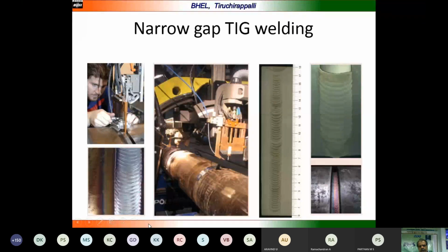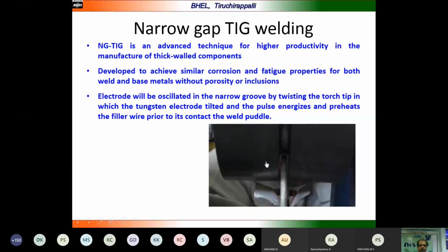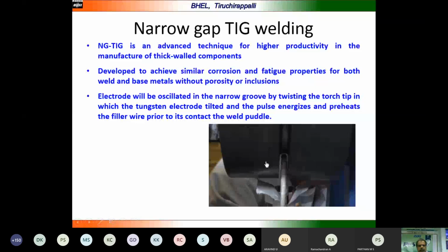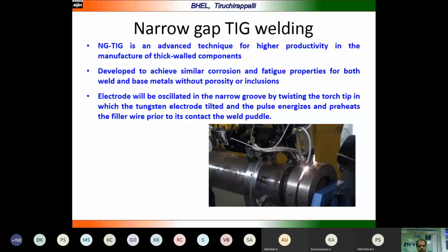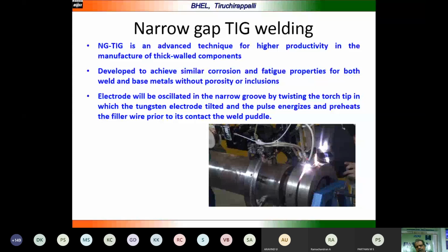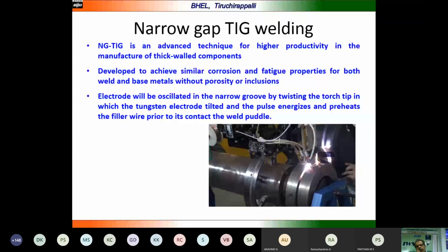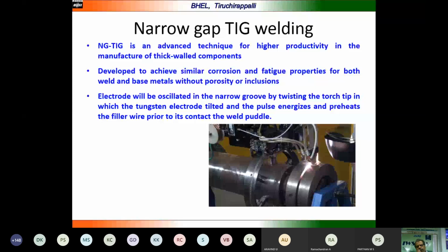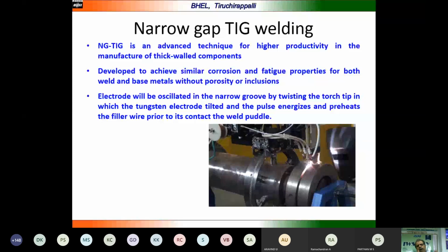The video is showing narrow gap welding, an advanced technique for higher productivity in the manufacture of thick walled components, developed to achieve similar corrosion and fatigue properties for both weld and base metals without porosity or inclusions. And the electrode will be oscillated. The advantage is that the electrode can be oscillated in the narrow groove by twisting the torch tip, and that is why the penetration can be ensured in all places. There will be no lack of fusion between the side wall and the job, and between the passes, because of the twisting of the torch.